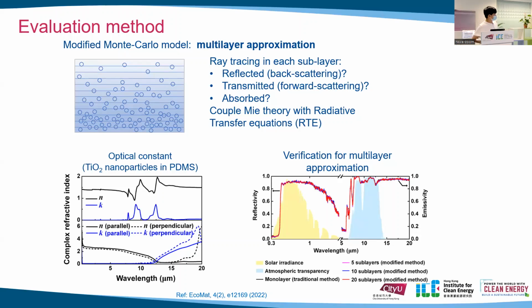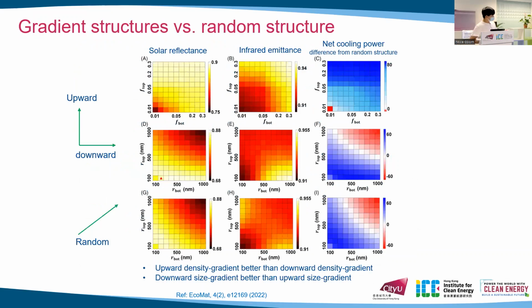The material we use for the calculation is PDMS as the matrix and TiO2 as the filler, and the optical constant is shown here. And we calculate a randomly dispersed structure using the traditional method, and then we divide it into 5 sublayers, 10 sublayers, and 20 sublayers using our modified method. You can find the result is the same. So our method and our multi-layer approximation is verified. Using this method, we can compare the spectral features of a gradient structure and random structure.